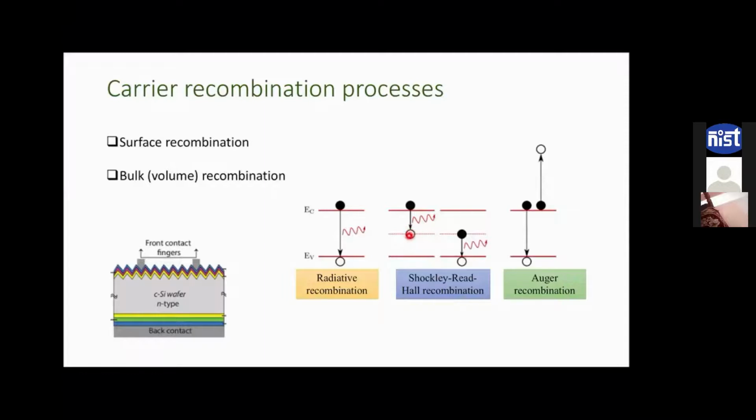One possibility is that the hole from the valence band will get activated to the trap site and recombine with the already existing electron here. Another possibility is that the electron will again relax into the valence band and recombine with the hole sitting there. Either way, we are losing charge. This kind of trap-assisted recombination is actually very dangerous for the health of a solar cell.